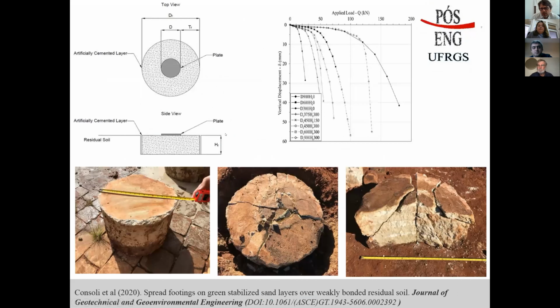Here is a paper also that was published in the second semester of this year in the Journal of Geotechnical and Geoenvironmental Engineering on the use of this same material to produce layers in the field. And in order to check if it was going to work in the field, we made this kind of material in real size. So we produced a size like 45 centimeters diameter and 30 centimeters deep, and this one 90 centimeters diameter and 30 centimeters deep. And we put some plates on the top of it. And then we carried out plate load tests in order to evaluate the strength of shallow footings that are going to be put on top of it.